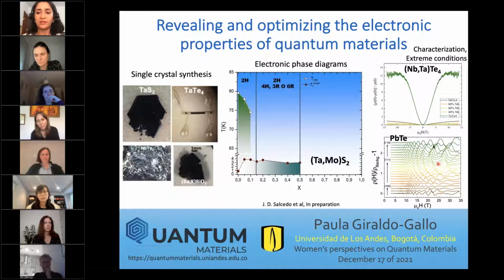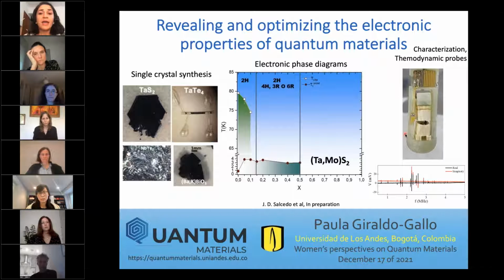So we go there and take beautiful experiments, like for example, in the compound lead telluride, which is a very nice thermoelectric material, very popular thermoelectric, but also a superconductor under certain dopings and certain conditions. All right, and we also use a little bit more advanced techniques other than transport measurements like the ones I showed. For example, resonant ultrasound spectroscopy, in which we measure the mechanical resonant modes of materials.